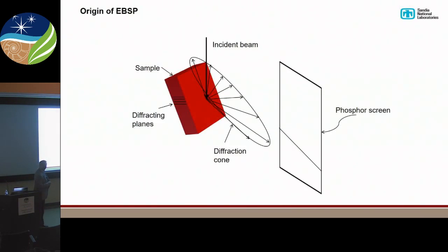If we look at what really happens in the microscope, so here's our incident electron beam, we actually tilt the sample over to some high angle. It really doesn't matter what angle that is as long as it's more than like 50 degrees or so. That does bring some operational difficulties because now when you move the sample around, it doesn't move in the plane you're used to seeing it move in, but we can work around that with modern computerized stages. So our electron beam comes in, impacts our sample. We have diffracting planes in the sample. We get diffraction from those planes. Those diffracted beams come out in a very flat cone. The apex angle of the cone is 90 degrees minus the Bragg angle, so Bragg angle is maybe a degree for 20 keV electrons. And so it's a very flat cone. We intercept that with a phosphor screen, and so it looks like a line. So that's where we see these patterns from.